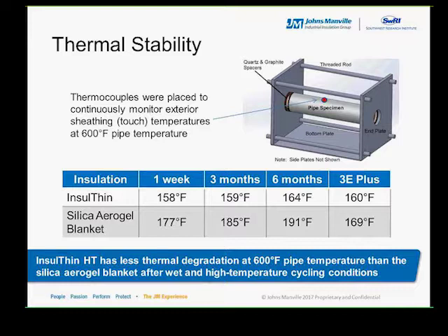So for example, at the 1 week mark, the temperature difference is 19 degrees Fahrenheit between the two insulations. You can see the 177 for the aerogel and 158 for the insulation. But after the 6-month test period, the difference increased to 27 degrees Fahrenheit. You can also see there 191 for the aerogel and 164 for the insulation. In addition, the temperature difference between the actual and theoretical expected values increased for the aerogel from 8 degrees to 22 degrees over the 6-month time frame, while the increase was only 4 degrees for the Insulthin HT.